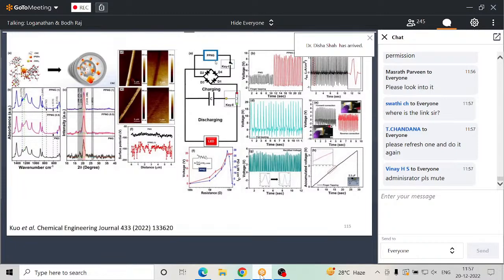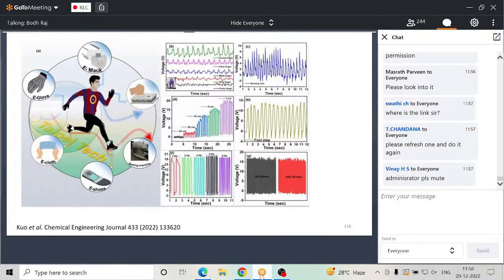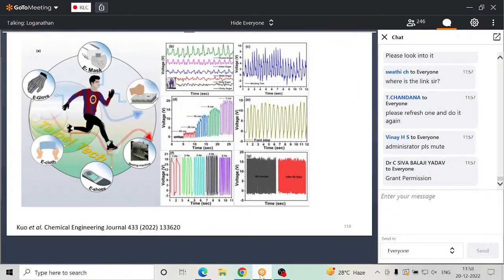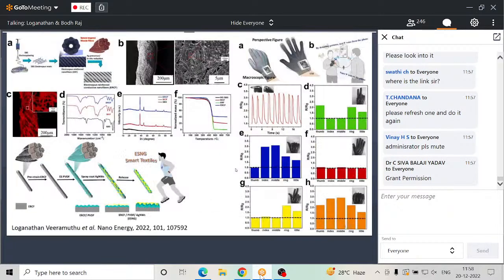So we form this kind of circuits and then we transform them into rectified voltages and then we study them and we can see the power outputs. And yeah, we can use these kinds of structures for e-mask or for shoe soles, cloths, gloves to sense. And then here we can see, depending on the intensity of your motion, you'll be getting different energy outputs. And we study the stability in the first 60 minutes, and even after 60 days, the voltage generation is quite stable.